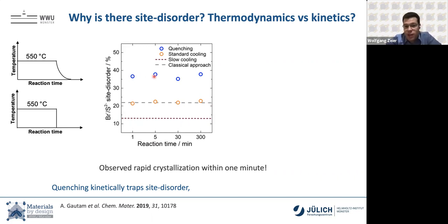If he runs it for 5 minutes or 30 minutes, or I guess that's 5 hours, still the same high site disorder, just by quenching. If he runs the standard cooling approach, we end back up at our 22%. This tells us that at higher temperatures, disorder is favored. At lower temperatures, it's less favored. So the quenching sort of kinetically traps the disorder. To corroborate that idea, we cooled the furnace in a slow cool approach over 5 days. Much more we shouldn't do, I guess. And the lowest site disorder we get is about 13%.